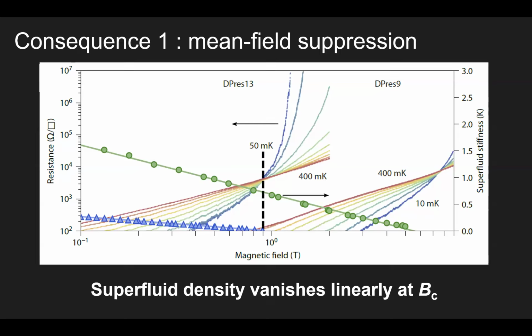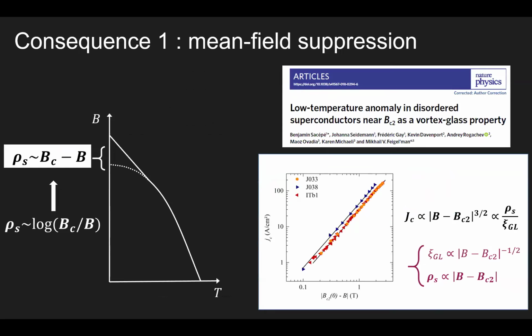And you can see that it coincides more or less with this transition. So the measurements have been done in situ on the same sample with the Hall bar separated from the resonator, and there is a pretty good matching. And this is important because a couple of years ago, we studied in low disordered samples what was called the low temperature anomaly. Turns out that these disordered superconductors always have a small deviation of the HC2 to magnetic field. Some people study that in the context of the quantum Griffiths anomaly. And we looked at it from a different perspective.